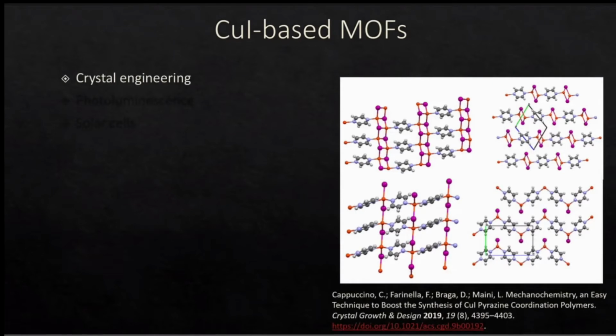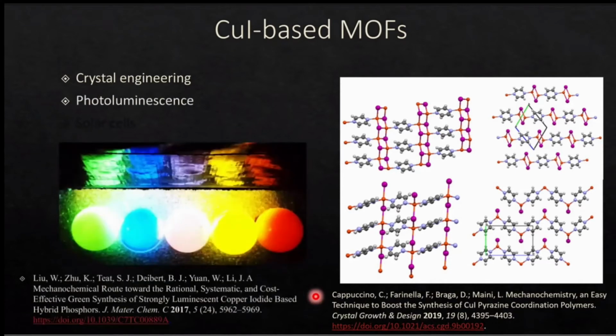To move into the more applicable region, these MOFs were first looked at for their use in crystal engineering, because most of these copper iodide-based MOFs have a very interesting property of having 2-dimensional or 1-dimensional structure. So the idea is you could expand a larger framework in only 1 or 2 dimensions in order to make more customized structures for crystal engineering purposes. The one that we spent the most time focusing on, though, is the photoluminescent properties of these materials. Whenever you shine UV light on a lot of these MOFs, they actually produce light in the visible region through fluorescence.